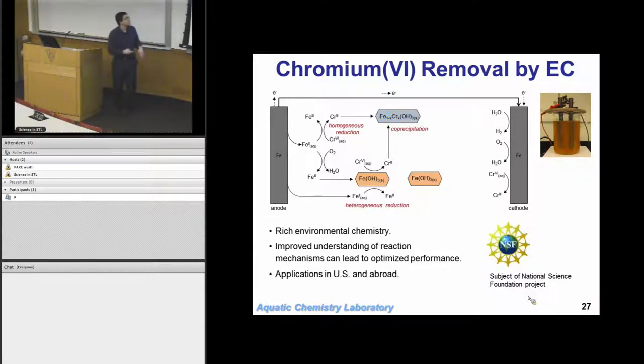And then that chromium 3 could precipitate with some of the iron, almost called a co-precipitate, so it's a mixture of chromium and iron. They're chemically very similar, chromium 3 and iron 3. They're almost next door neighbors on the periodic table. They're the same charge and they have very similar ionic radii, so they can form co-precipitate nicely. And we could absorb some of the chromium and the chromium 6 onto the surface of these particles. So it can work to remove chromium 6, and also I think that chemically it's really interesting.